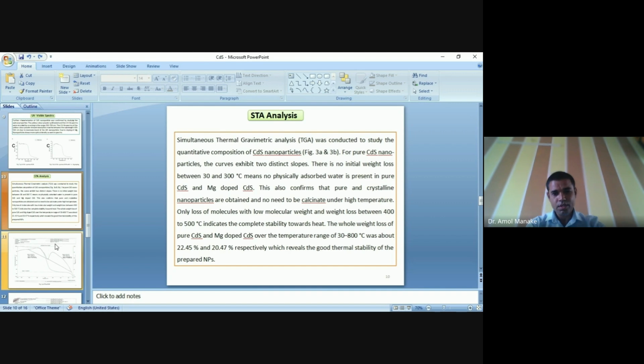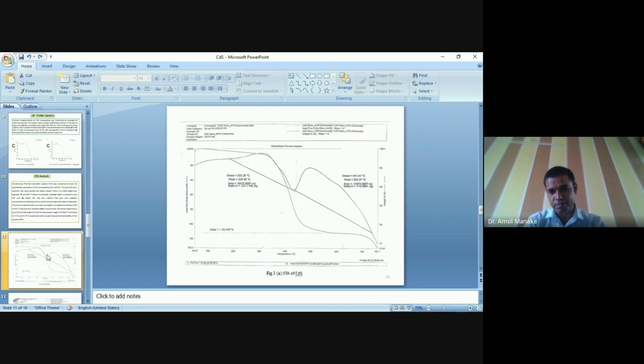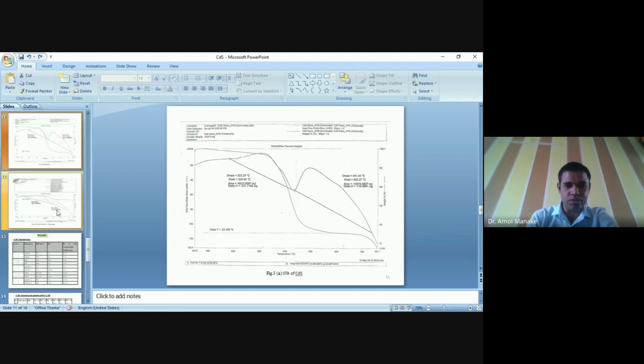Yes. The weight loss is only 22.45% and 20.47%. This is the STA spectra of the pure cadmium sulfide nanoparticles. Here we can clearly see the delta Y, which is 22.45, meaning it is the total weight loss of the compound. From the 100%, only 22% of the weight loss is there, showing very good thermostability.